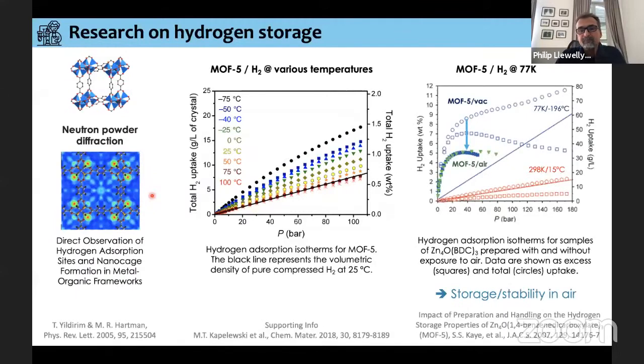Just to make the point again, on the right-hand side, these authors have looked at materials that have been initially prepared under vacuum, and we get quite nice high uptakes of hydrogen here. They compared this with a material that was left aged a little bit just in air, and we can see that there's quite a large decrease in capacity. So this is just again to make the point that some materials aren't so stable. We have to be careful of storage and stability in some cases.